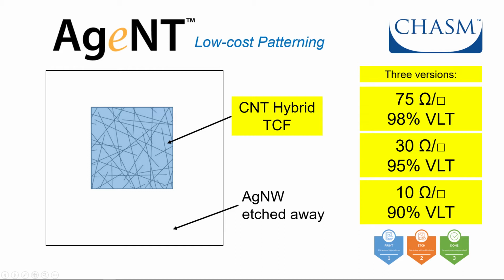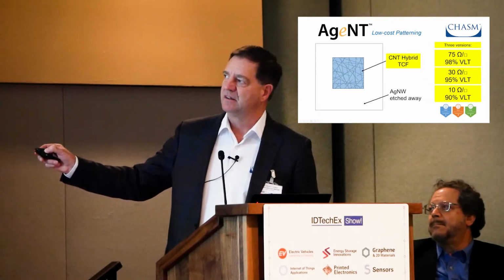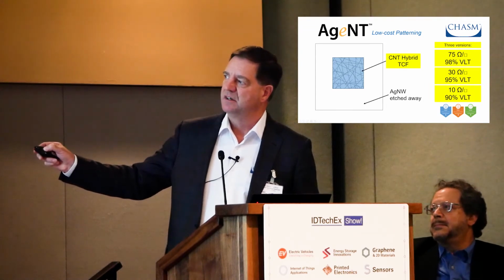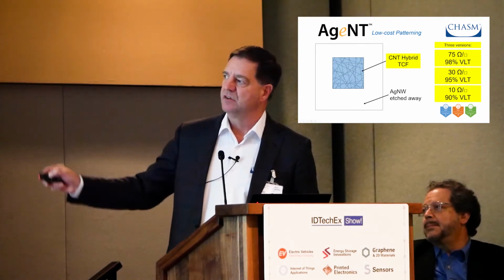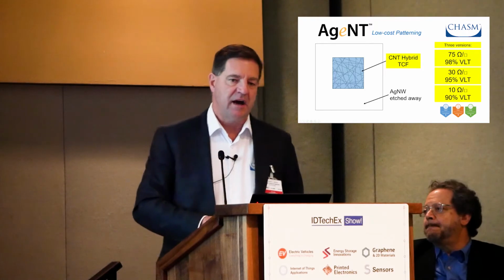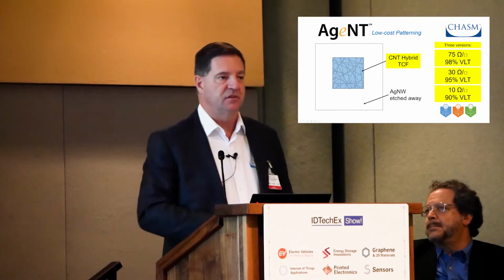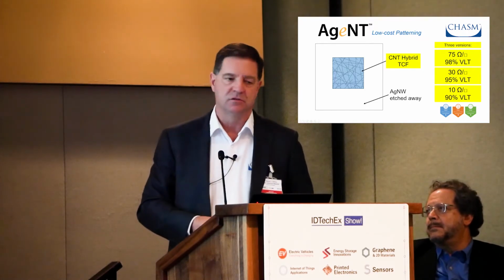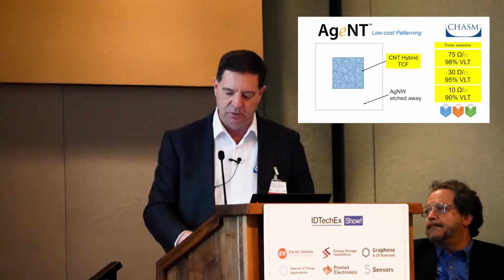square. The ohm per square is mainly dictated by how much silver nanowire areal density is in that film. And there's an expected trade-off in transparency, 98, 95, and 90% for these 3 different ohm per squares. We have 3 different ohm per squares because different applications require different values of sheet resistance. And I'll explain that a little bit more later.